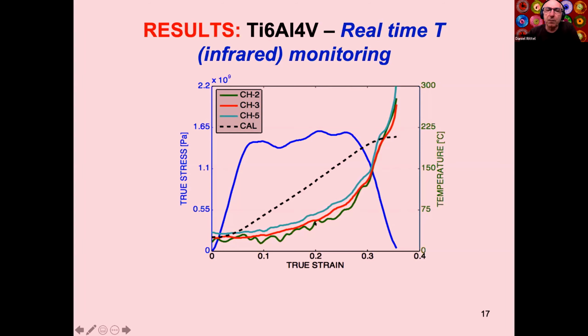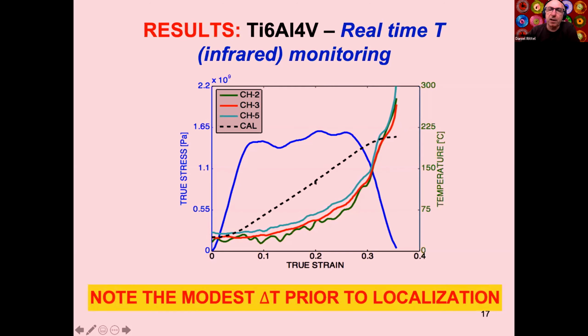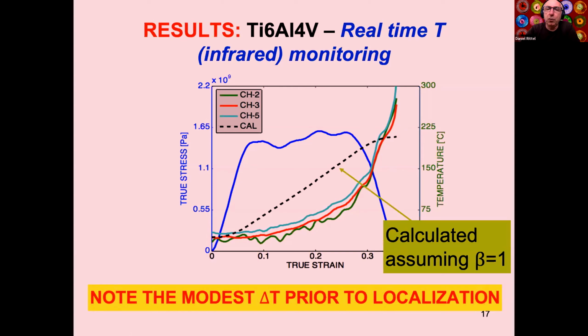We have three active channels. We're testing titanium 6, aluminum 4, vanadium. And in blue, you have the stress-strain curve. And those three lines here are the temperature rise. And the dashed line is the one that you would obtain if you converted 100% of the mechanical energy into heat. Okay, so we can measure in real time. Here the strain rate was about 3,000 per second. We can measure the temperature of a deforming gauge of a specimen.